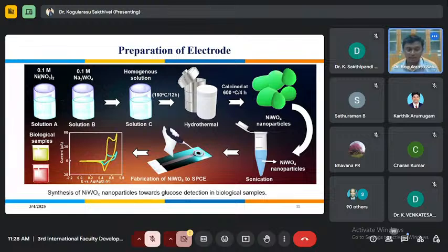The reason for choosing this material is, of course, we know that the tungstate is more stable and the nickel is more conductive. So the synergetic effect of this material is renowned, so we have used it for this kind of glucose biosensors. And this is how we prepared. First, we make it as a homogeneous solution and we synthesize through the hydrothermal technique. After the hydrothermal synthesis, the precipitates are collected and it is calcined at 600 degrees Celsius for 4 hours to remove all the impurities from the nanomaterials.